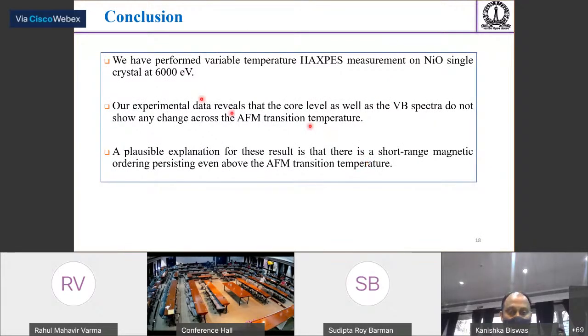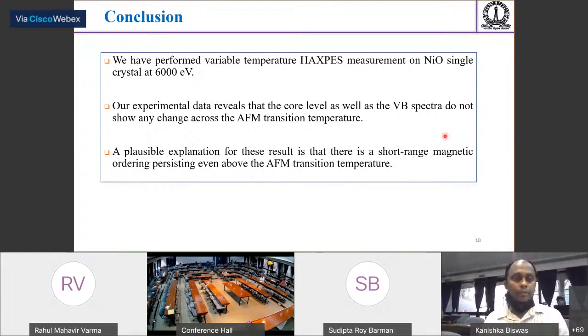In conclusion, we have performed variable temperature measurements on a nickel oxide single crystal. Our experimental data reveals that the core level spectra and the valence band spectra do not show any changes across the antiferromagnetic transition temperature. And the possible explanation for this is that there is a short-range magnetic ordering, which even persists above the transition temperature.